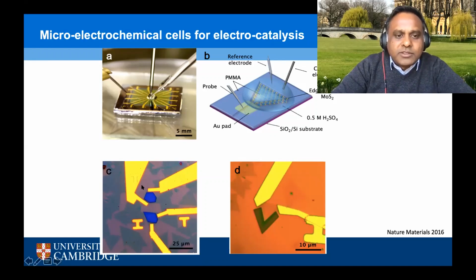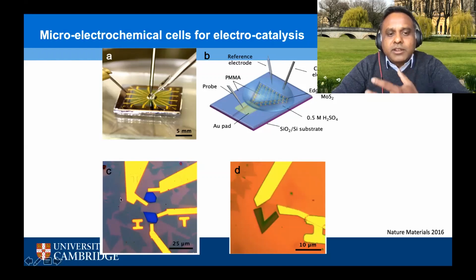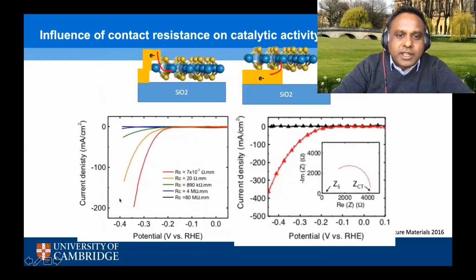But one study that we conducted a few years ago was to look at the influence of contact resistance on electrocatalysis. So of course it's not surprising for us that if the contact resistance is high, as shown here, the catalytic activity is poor. So here, this is plotting the current density as a function of the applied potential for a reaction to occur. And the higher the current density, the better the reaction is proceeding. And one can see that for a low contact resistance, the reaction and the current density is much better. And so this charge injection and improving the contact resistance between the catalyst and the support is a very important parameter that was neglected, in our opinion, by the electrocatalysis community for a long time.